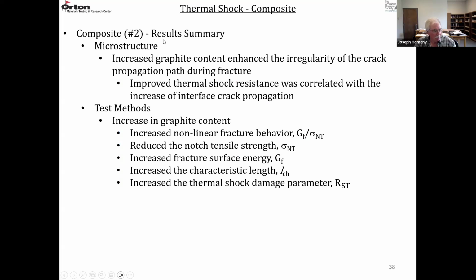So the summary of this experiment: increased graphite content enhanced the irregularity of the crack propagation path. It made a more tortuous fracture path, and that improved the thermal shock resistance because of this more tortuous propagation path.